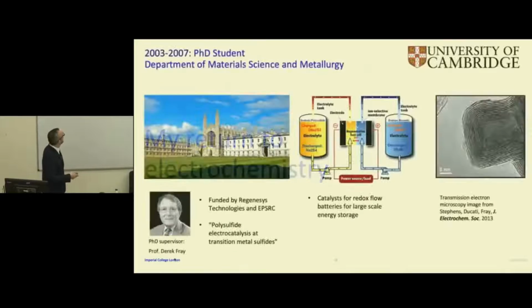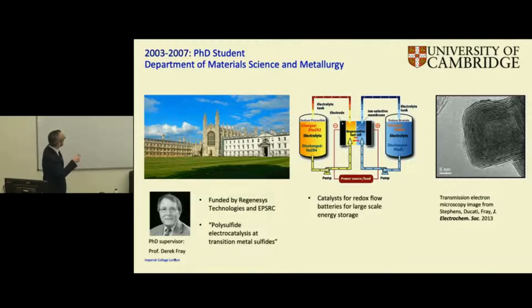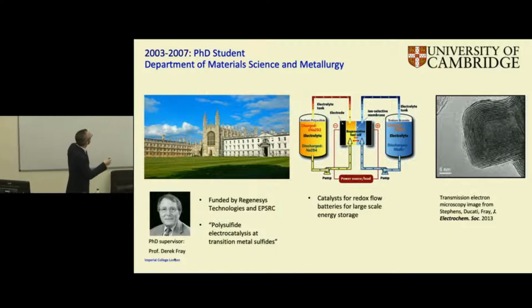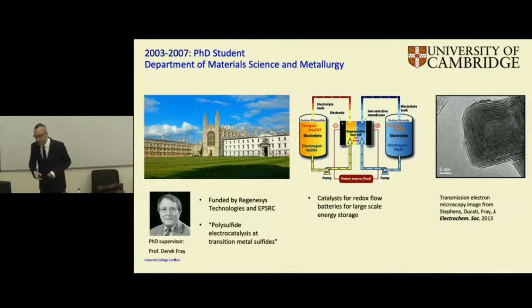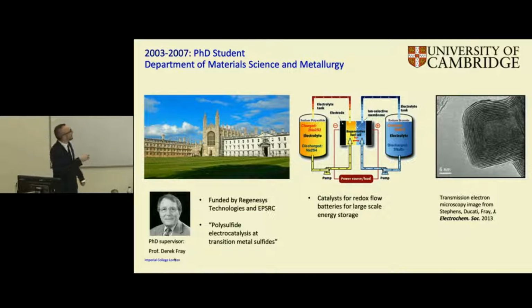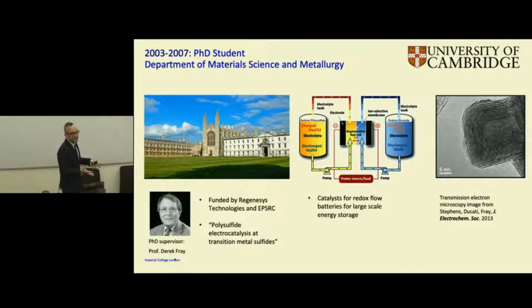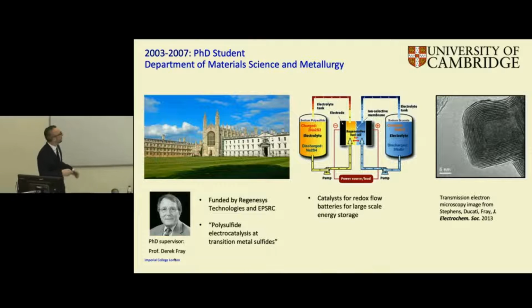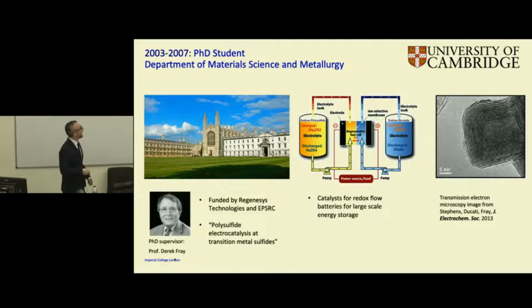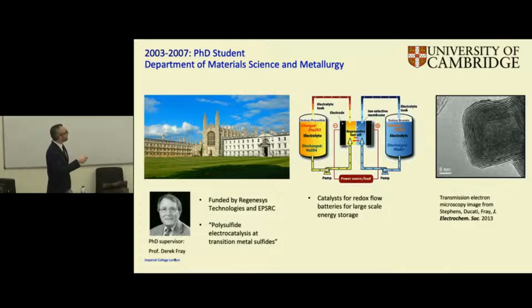So I went to actually do a PhD at Cambridge University. The supervisor was Derek Fray. What I looked at was catalysts. This is the first time I actually started working with catalysts for redox flow batteries. Redox flow batteries are like a regular battery, except that you charge up a solution and you store it in a separate tank. The reason you store it in a separate tank is that in a regular battery, the amount of energy you can store is controlled by the dimensions of the cell. But if you store it in a separate tank, you decouple the two. So this would be really useful for large-scale energy storage. The premise of my PhD was that these special transition metal sulfide materials would be really good as catalysts.